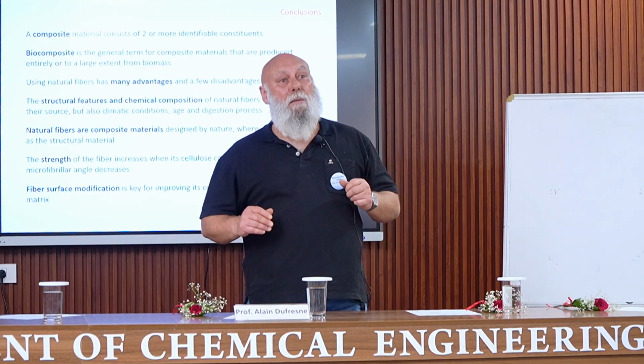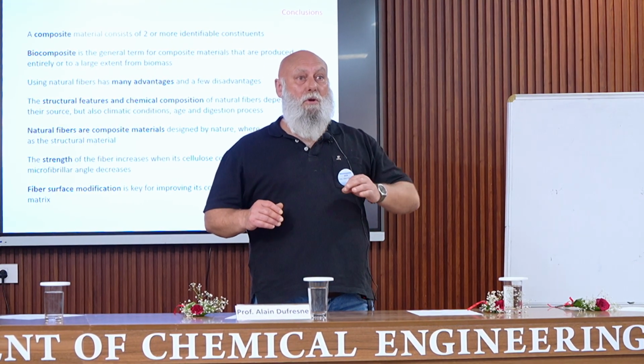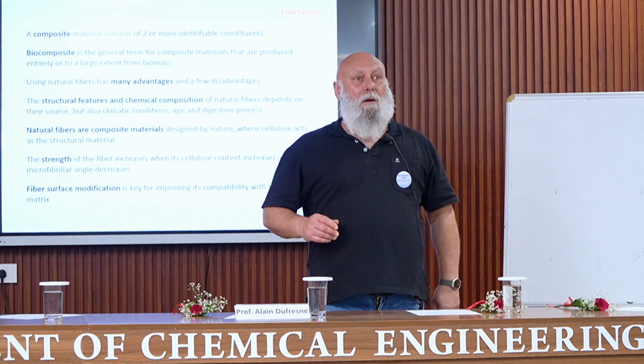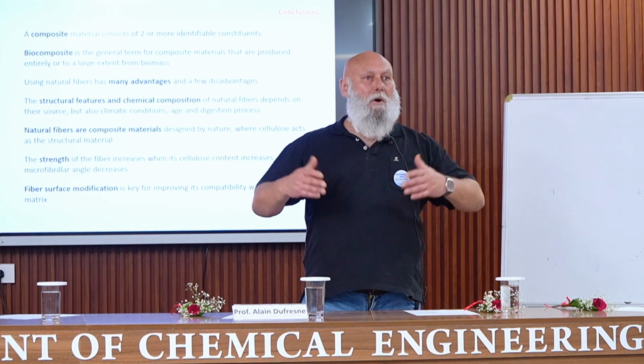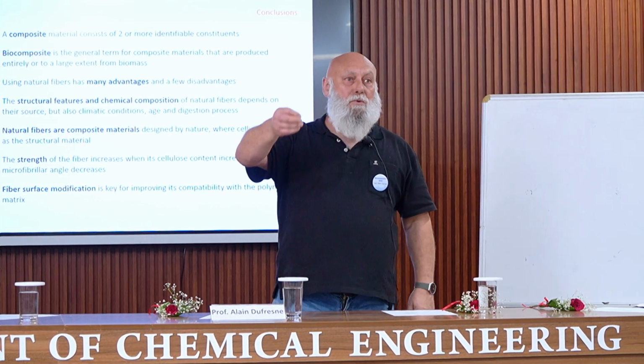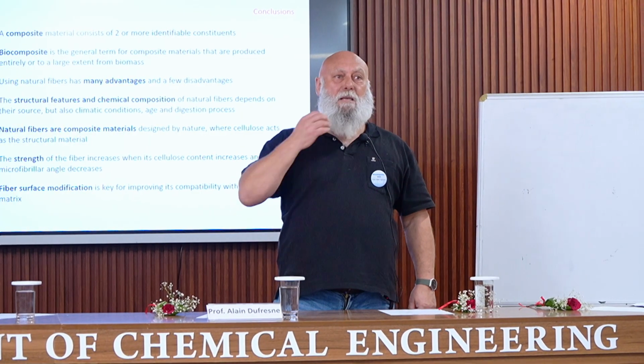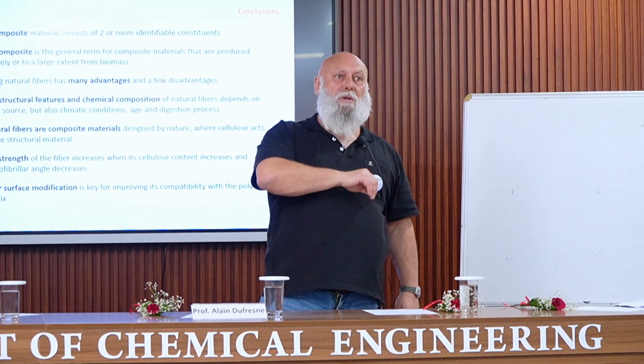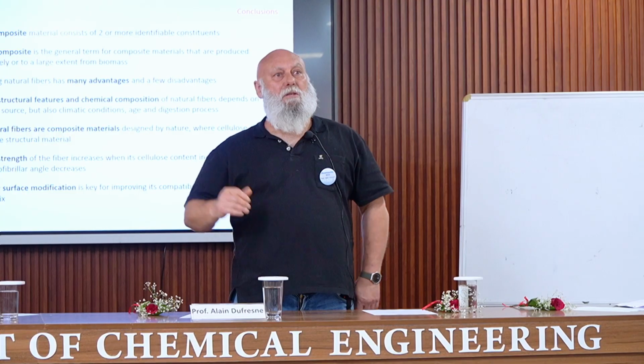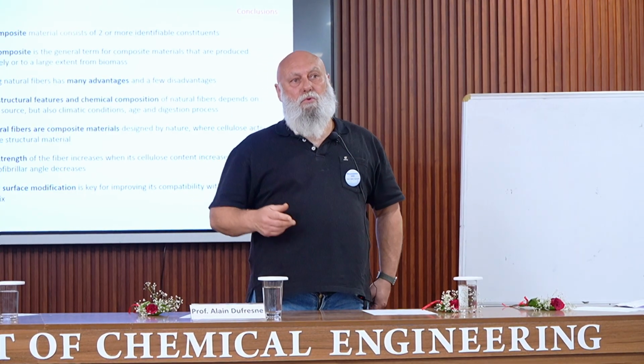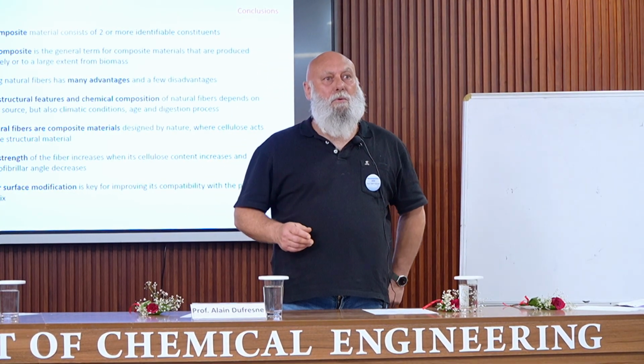This is the case, for example, for cotton. Cotton is almost pure cellulose. But for other sources, if you want to extract cellulose, of course, it's necessary to have this alkaline treatment followed by a bleaching treatment, which are the two treatments which are generally used.